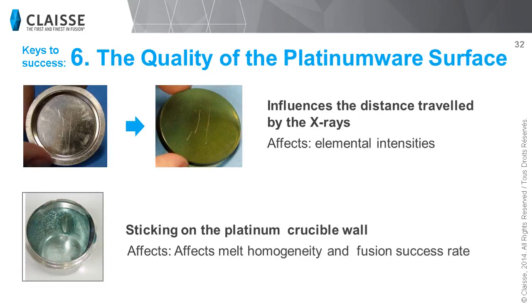Talking about sticking, it is also possible that you may need to use a non-wetting agent in your fusion mixture depending on the application. The non-wetting agents, which are usually halides, decrease the tendency to stick to platinum ware. The most common non-wetting agents are lithium bromide and lithium iodide.